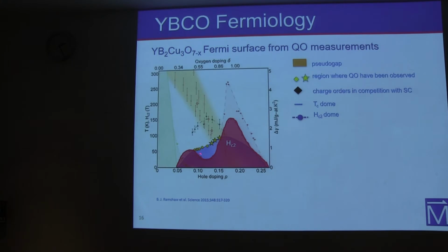So this is here the estimated dome of the critical field. To measure those samples, you can either use 45 Tesla in Tallahassee and you have access to this range of doping, or go to Los Alamos and use the 100 Tesla magnet and you can access this region. But to go to a higher field is really difficult, and actually the estimate is that to go to optimal doping, you have to reach beyond 150 Tesla. So right now it does not exist, or it's really complicated with different magnets.